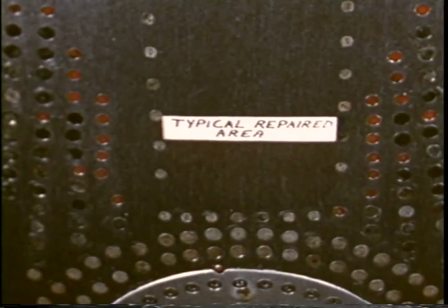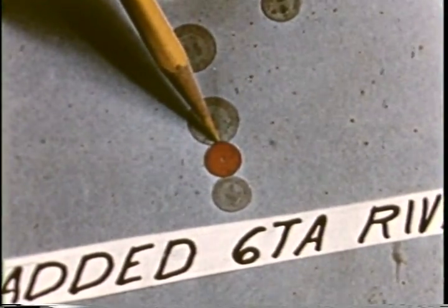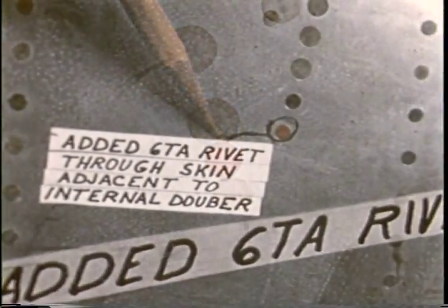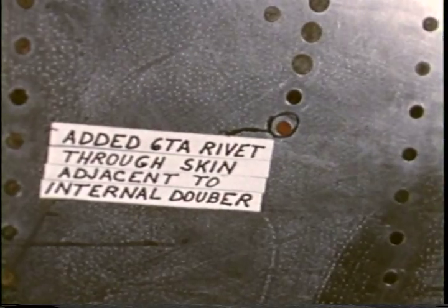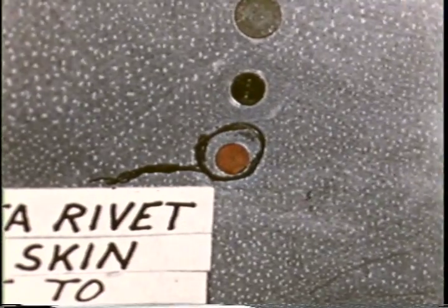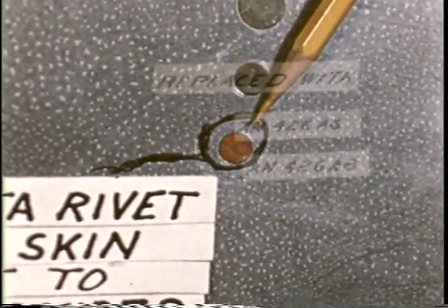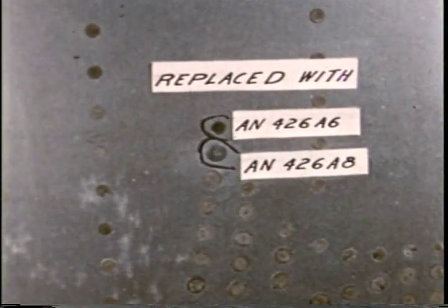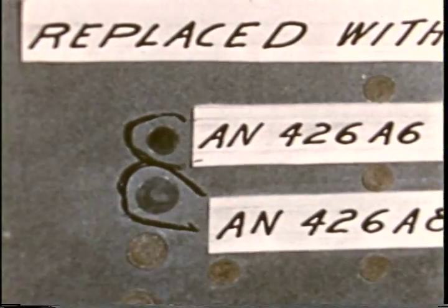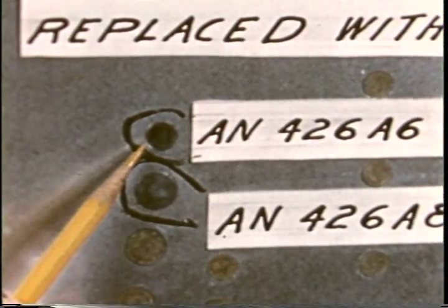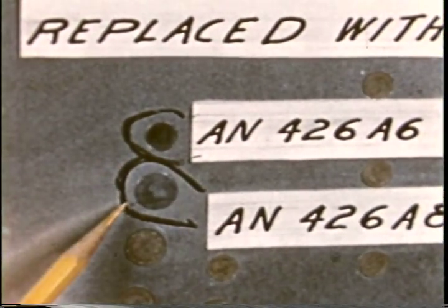These cracks were then repaired with maintenance type fixes. Stop holes were drilled in the cracks and internal tapered doublers added to reinforce the area. The repairs were then evaluated by subsequent cycling. Preventive fixes were also tried, such as using double rivets to reduce the stress concentration on what would normally be the end rivet. Evaluations were also made of a rivet added in front of the internal doubler in an attempt to reduce the stress concentration on the end rivet. The end rivets were replaced with very soft rivets in another area. These preventive fixes were all evaluated, and from these tests, corrective action was taken.